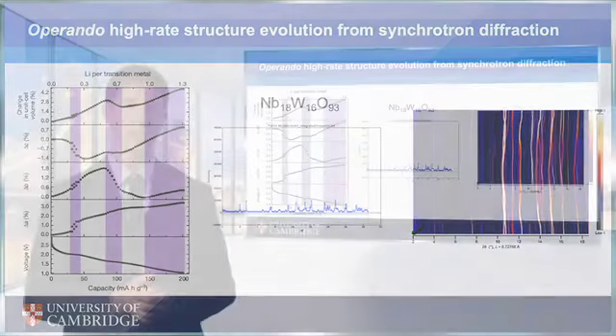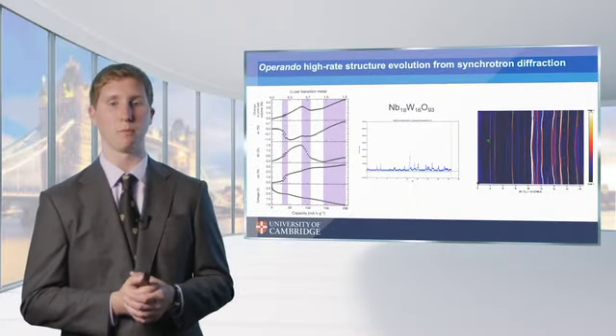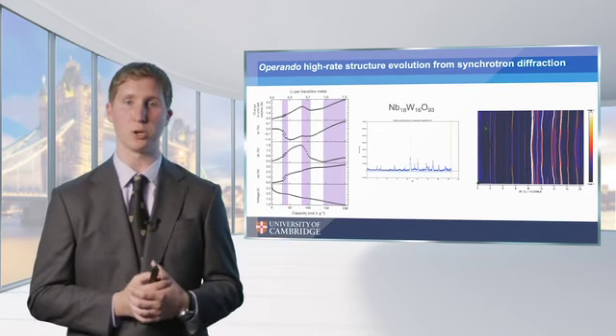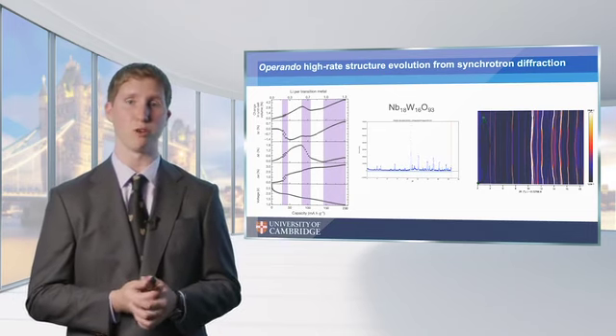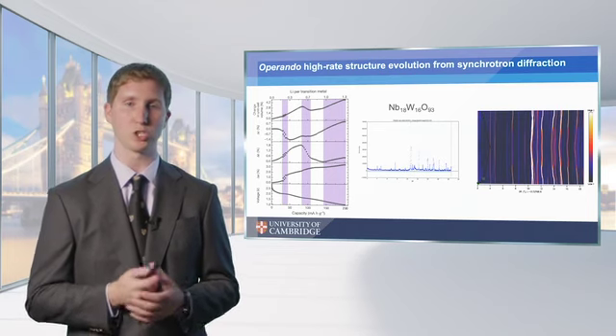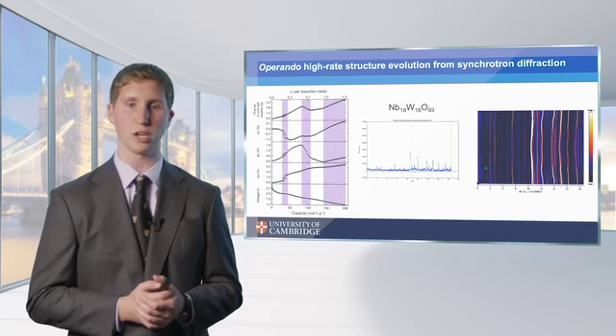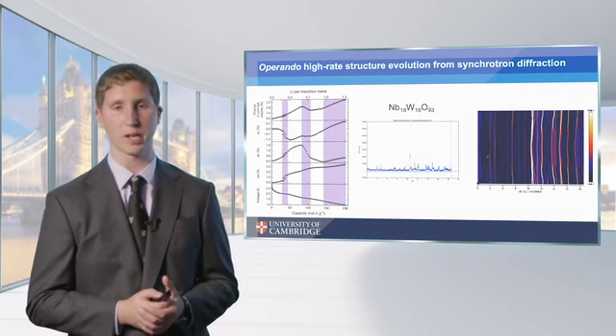So we just have a lithium miscibility gap, maybe in how much lithium can be in this phase before it swaps. But the overall mechanism of having an anisotropic volume expansion is so strong in this structure that actually, as you go from about 50% state of charge down to fully lithiated, the whole volume of the structure contracts. And so this leaves you with a fully lithiated Li34 NB18 W16093, which has only about a 2.5% volume expansion. So very, very small volume expansion, which is certainly going to be helpful when we're trying to cycle these structures thousands of times without having degradation and cracking.